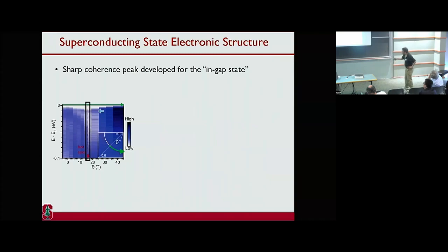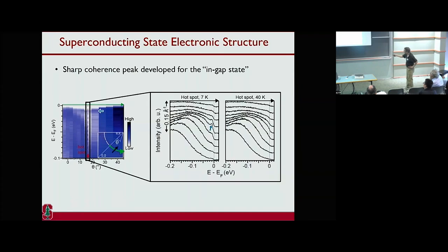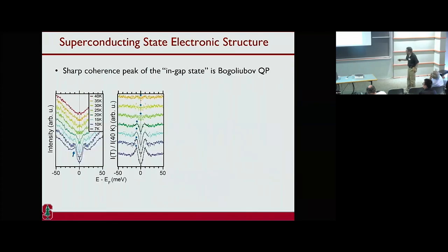Now, if I take one slice, then that is the one here. Okay, that's the spectrum. You see a higher energy pseudogap. Inside the gap, you see a feature, and this feature shows up below TC. Okay, so it's not the impurity state they give to you. That's the one that gave you the Bogoliubov quasiparticle. Okay, and now you can also show that, hey, indeed, with this temperature dependence, this feature goes away at TC.